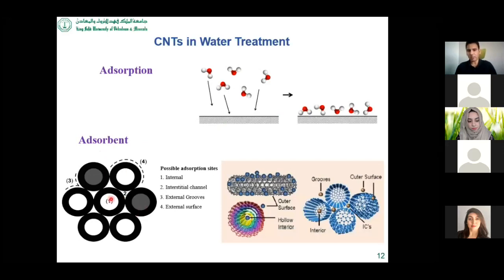This is a bundle of carbon nanotubes. Remember that carbon nanotubes usually tend to agglomerate due to van der Waals forces, and they will be held together by these forces. Of course, this is one of the major challenges: we should develop some technique to properly disperse the carbon nanotubes for various applications. These are various carbon nanotubes, and here this closed tube represents where the metal catalyst is. When they come directly from the CVD, you need to remove the metal catalyst first.